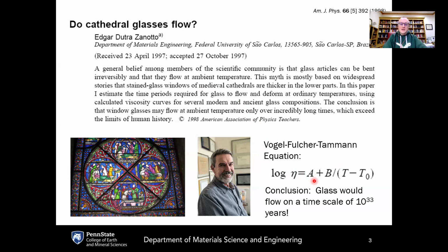But based on that extrapolation with this VFT equation, Professor Zanotto concluded that glass could only really flow on a very long time scale, on the order of 10 to the 33 years. So not just longer than all of human history, but longer than the history of the universe itself. So his conclusion is that this is just a myth and that glass was not actually flowing at ambient temperatures.